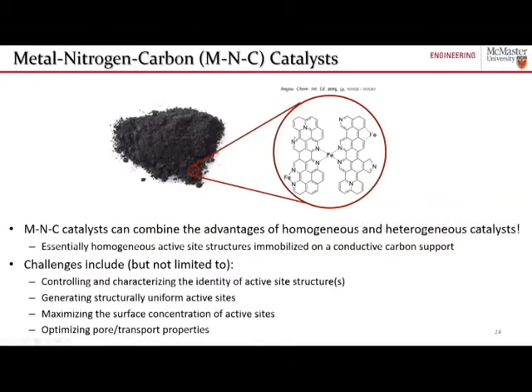So what metal, nitrogen, carbon catalysts can do is they can actually combine the advantages of both homogeneous and heterogeneous catalysts. Because ultimately, at the end of the day, it's hypothesized that the active site structures in these materials are essentially homogeneous catalytic structures that are immobilized on a conductive carbon support. But there are some challenges related to the preparation, development, and understanding of these materials.